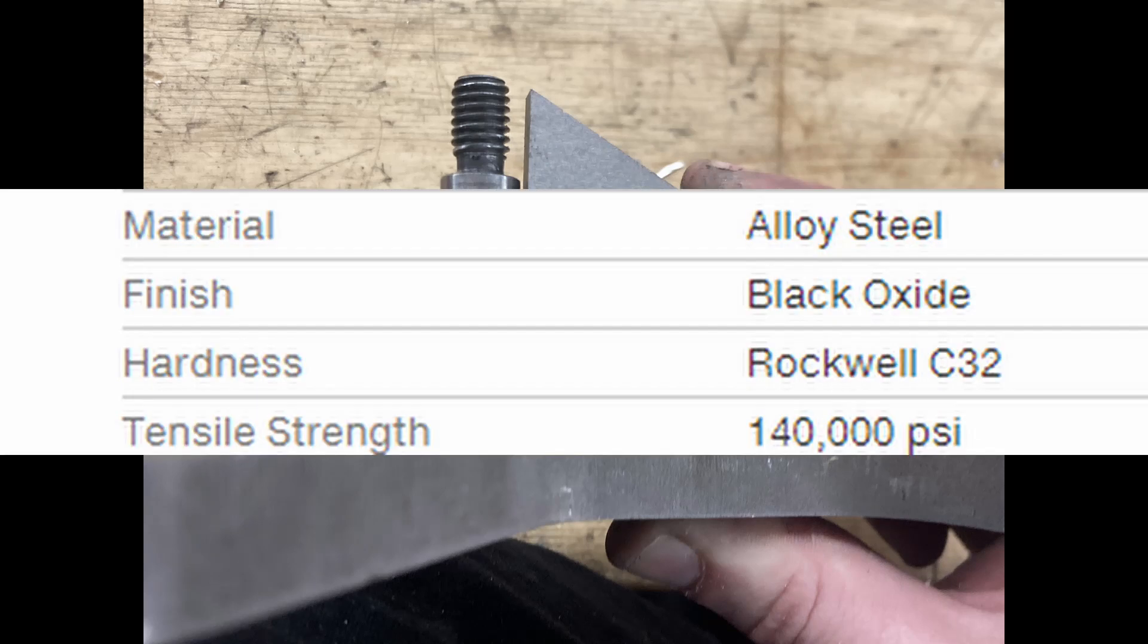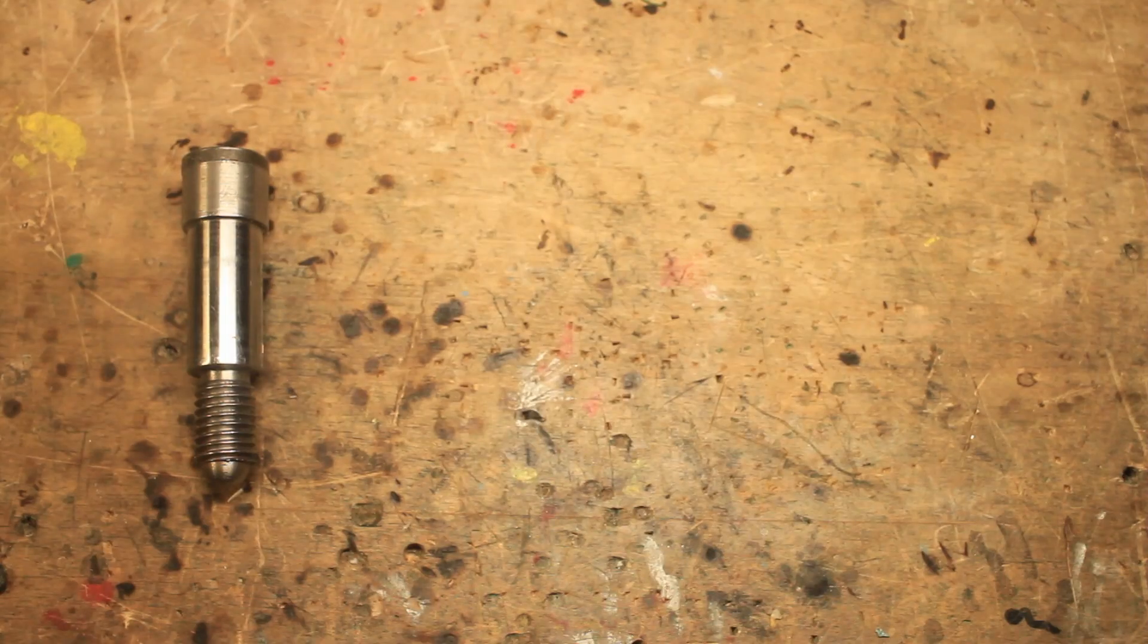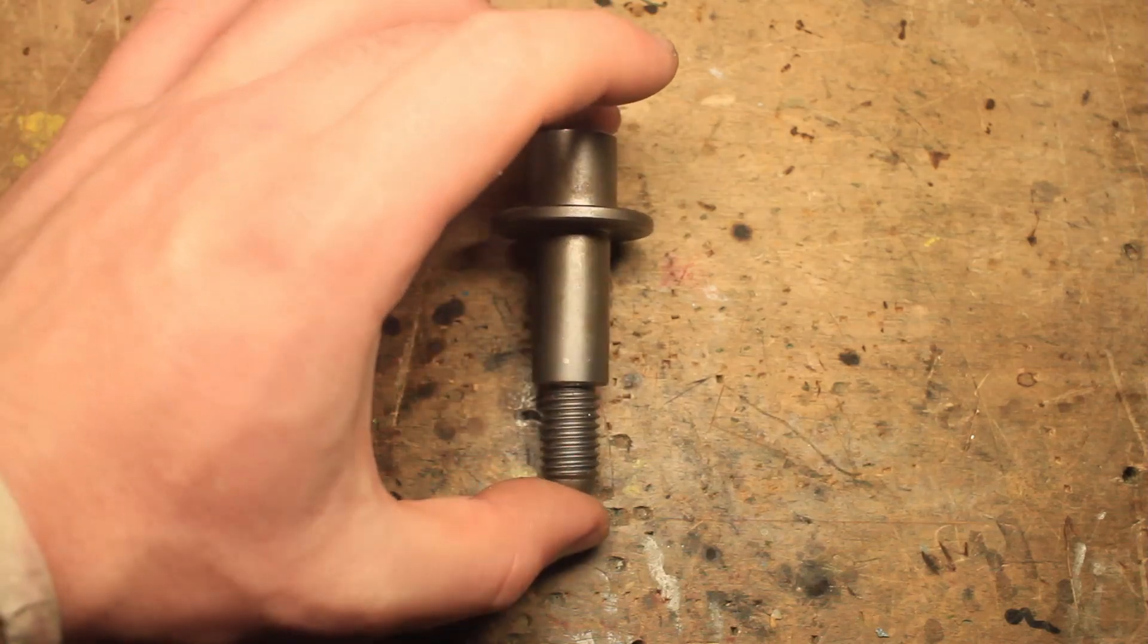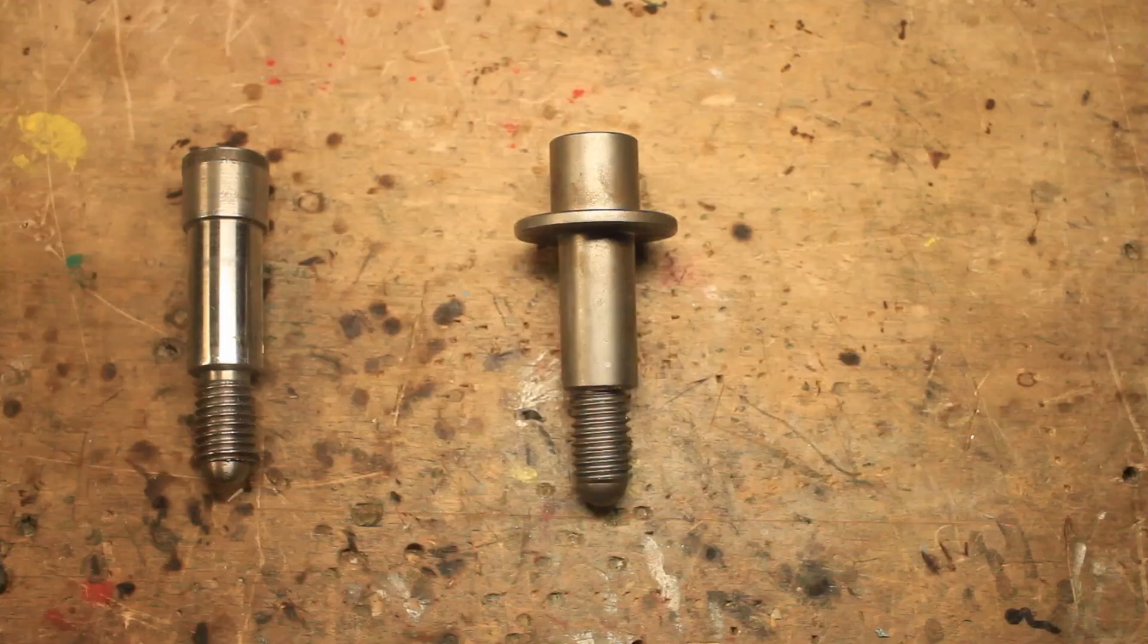I think the tail is longer, which is absorbing more impact. But I also think the old shafts were softer, which resulted in a higher impact strength. When I had the flange shafts made, they were hardened to 49 HRC, which has significantly less Izod impact strength.